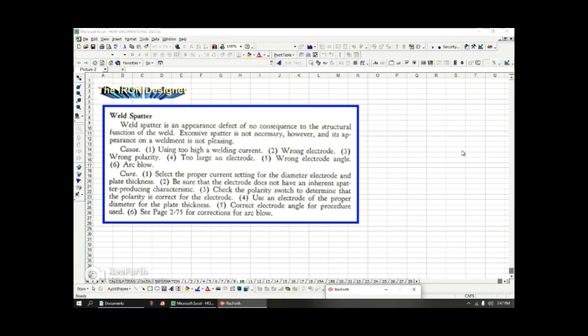Another indicator that you have too high of a current is you're going to have weld spatter. It's like if you're cooking food and your food is just spattering all outside of your pan, you could get the same thing when you're welding. You have too much current, it's bubbling the molten metal too much and causing the metal to spatter out of the weld, and that's a sign and indication that your current is too high and your weld is not going